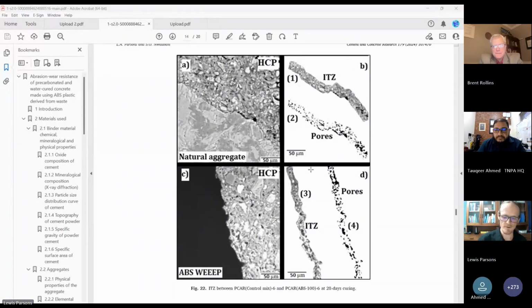Now, as you know, one of the weak links within concrete is the interfacial transition zone. It's completely different to that of the bulk paste. And this is shown over here. Generally, we find that the interfacial zone goes from a more highly porous microstructure to one similar to the rest of the bulk paste. We generally find it ranges anywhere from, people have said, 5 micrometers all the way to 30, 35. I generally say it's around 30, 35, even though some might go to 100, which I do not necessarily agree with.